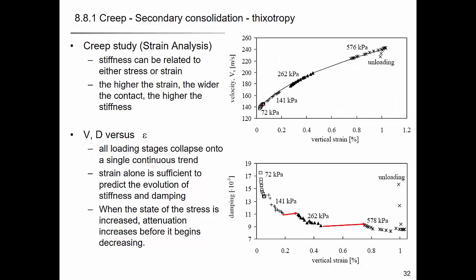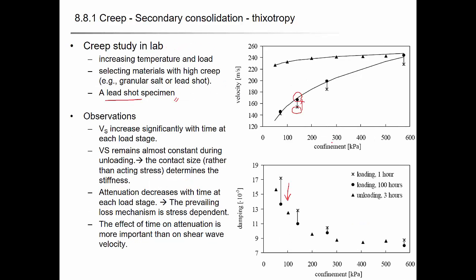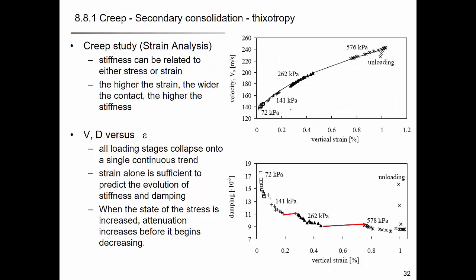And when you plot the velocity against the vertical strain, before it was against the confinement, right? When you plot the wave velocity and the damping ratio against the vertical strain, it actually follows just one unique line, right? So this wave velocity can be correlated to the vertical strain, and vertical strain you can change to porosity, or the void ratio.